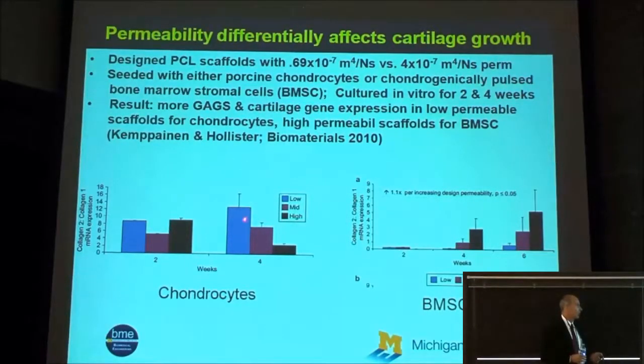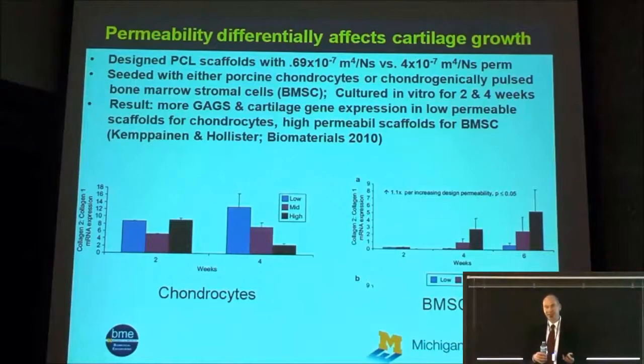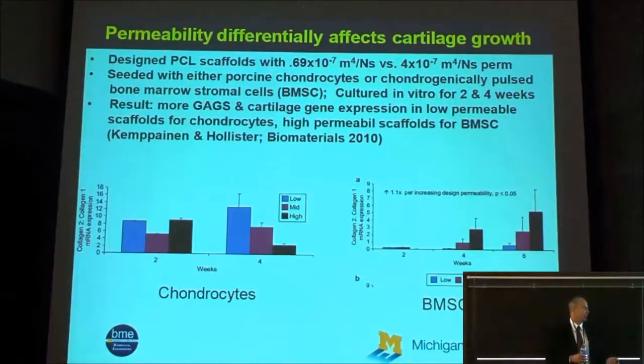This is totally an in vitro study. But what we found in terms of both GAG production and gene expression for collagen 2 being more prevalent in cartilage matrix than collagen 1, chondrocytes do better if they're in a lower permeable environment, at least in vitro, whereas chondrogenically pulsed BMSC do better in a high permeable environment. And probably for a BMSC, because part of the thing you're doing is pulsing them, you're giving them growth factors in the fluid, the more you can get that fluid into the scaffold, the better for those cells, and that's probably why they express more cartilage genes and make more cartilage matrix when they're in the higher permeability scaffolds.